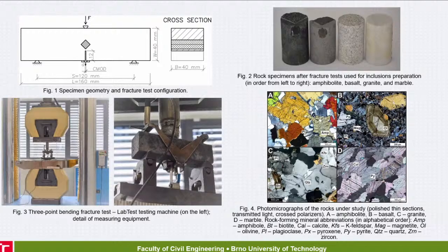So, first of all, to determine the influence of the interfacial transition zone on fracture behavior of cement-based composite, a special specimen geometry was designed. As you can see in figure 1, it was a prism of the dimensions 40 times 40 times 160 millimeters with internal inclusion of the dimensions 8 times 8 times 40 millimeters. The inclusions were made of rocks, as you can see in figure 2.